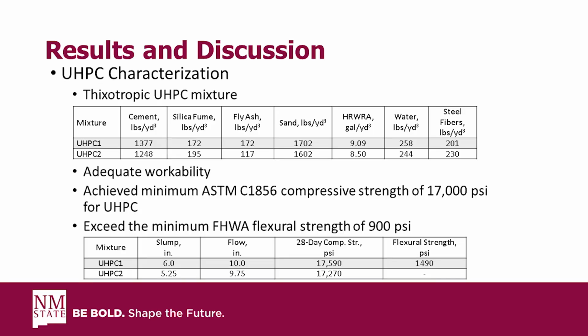We want it to sit still until energy is put in to move it with the vibrating screed or vibrating needle. So we have 2 UHPC mixtures here, with the first one, we replaced 20% of our cement with supplementary cementitious materials that's made up of a 50% blend of silica fume and fly ash, so they'll have the same number there for their mass. And for this mixture, we had a 0.15 water to cementitious materials ratio, and we used 1.5% of steel fibers. And UHPC2, we're taking out 20% of our cement, replacing it with, in this case, 62.5% of silica fume, 37.5% of our fly ash. And for this one, our water to cementitious materials ratio is going to be 0.145, and our steel fiber content is going to be 1.75%.